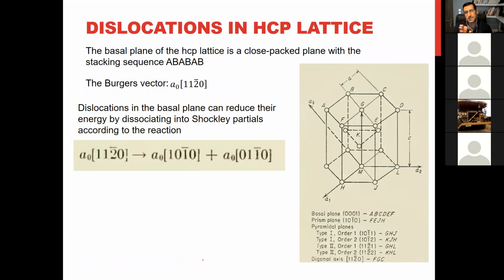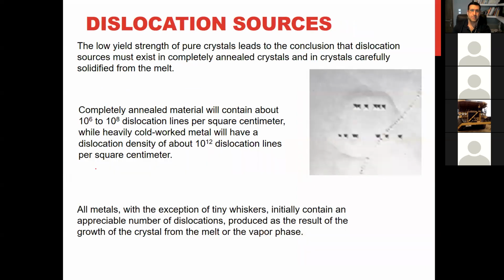That was FCC. In HCP we also have the same, as this basal plane has a similar configuration. Deformation can also happen by partial dislocations, and the decomposition of the dislocation for HCP is like this, becoming two partial dislocations. You can also calculate the energy of each dislocation and understand that the sum of these two is less than this, so this decomposition can happen easily. For HCP dislocations, there is not much more that we can talk about. And dislocation sources we also talked about.